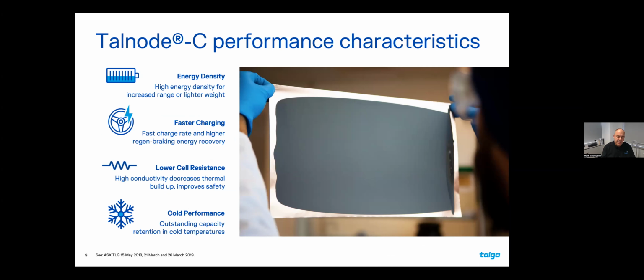Our main product, Talnode C, is qualifying with numerous companies now. It's quite deep into qualifying. It's at a B, and with some groups even a C stage. It is characterized compared to other materials as being quite energy dense. It's got quite high capacity, works really well at lower temperatures in particular. It's got very low resistance. So it works really well as a blend with synthetic for EVs, or it can be used 100% for some EVs, but also other markets as well, like ESS, stationary storage, or what's called the 3C market, which is quite exciting in itself because it's things that have also got interesting growth trajectories, like power tools, things like carpet cleaning robots and vacuum cleaners and drills and all sorts of devices.